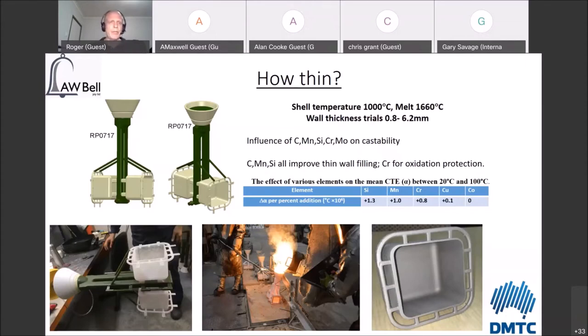And so you can see the model of the parts, the trial parts on the tree up in the top left corner, actually on the tree being manufactured in the bottom left, casting in the middle where the shell's been preheated at 1,000 degrees and the metal temperature was 1660. And on the right-hand side is one of the finished results.